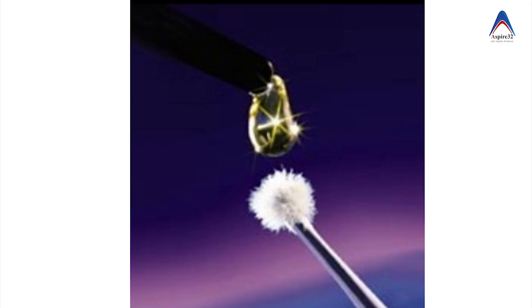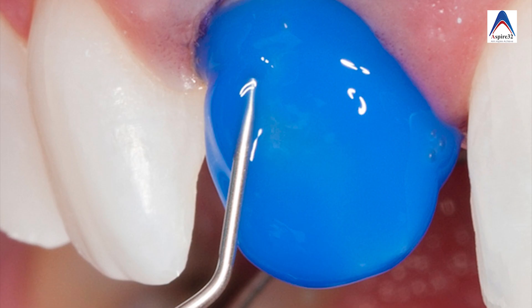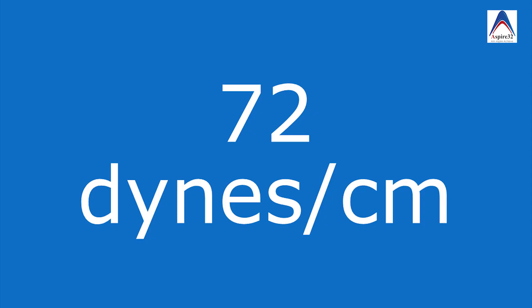The third reason for increased bonding is its ability to increase the surface energy of the enamel. The bonding agent is actually hydrophobic and has less penetration into the enamel tooth structure. When you etch the tooth structure, the surface energy increases drastically. The etched enamel shows a surface energy of around 72 dynes per centimeter, which is two times more than unetched enamel. With this high surface energy, the bonding agent is attracted towards the enamel surface by capillary action, leading to increased bond strength.